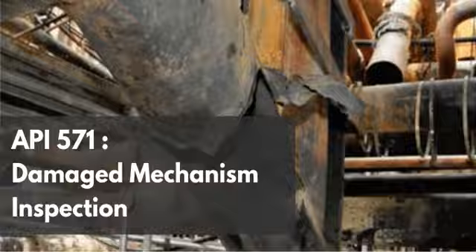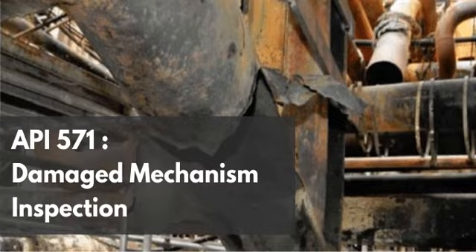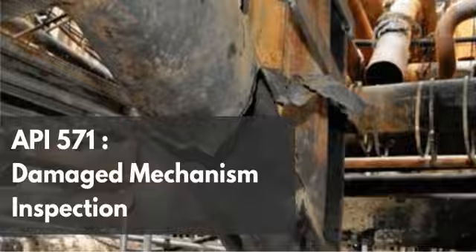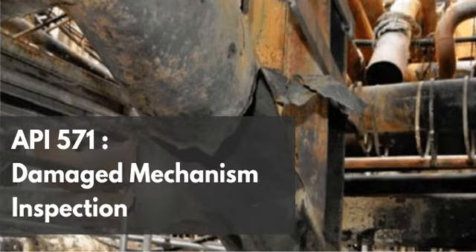You're absolutely right, and that's an important nuance. There are always trace elements. The specifications that govern these materials, like an ASTM A516 for plate or an ASTM A106 for seamless pipe, permit small amounts of specific elements. These elements are usually artifacts of the steelmaking process or are left in because they positively affect basic properties like hardness after welding, toughness, or basic deoxidation. We're talking about small quantities of manganese, chromium, nickel, molybdenum, copper, sulfur, silicon, phosphorus, aluminum, vanadium, and sometimes boron.